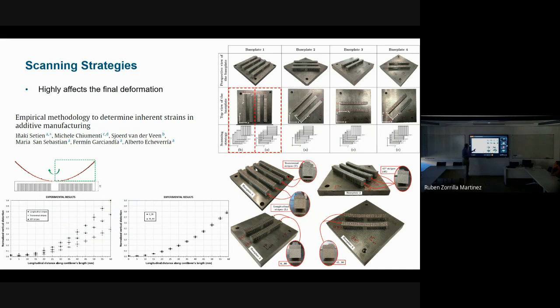And these are the normalized deformations of those prints. You can see that this is normalized to 1, and this was the longitudinal one. If you print everything in the transversal direction, then you get almost half of the deformation. But the good point is that with any of those patterns of, let's say, rotating each layer, you get about 80% of the deformation, but it is not orthotropic, it is at least isotropic in the plane. This is the reason that people usually go for the rotating one.